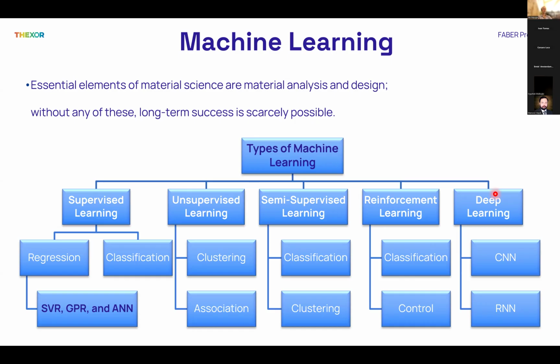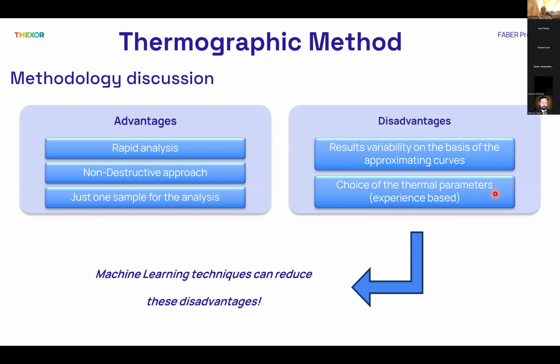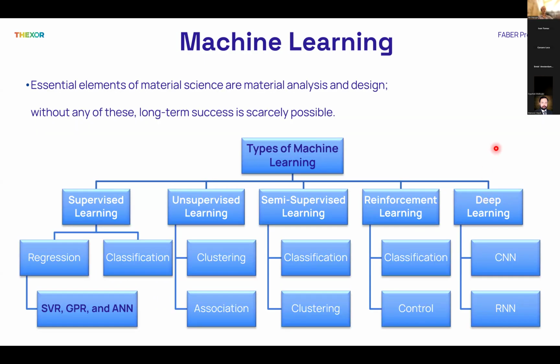So as Dr. Corsaro said, one of the main disadvantages of the TCM two curves method for fatigue life estimation as an NDT technique is the high uncertainty. So you can have a batch of highly variable results from each other with a wrong range threshold. And as Dr. Corsaro said, the choice of thermal parameters is completely based on the experimental campaigns you are delivering. So we were thinking that maybe machine learning could be useful.